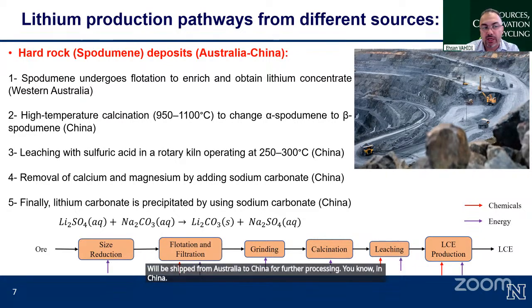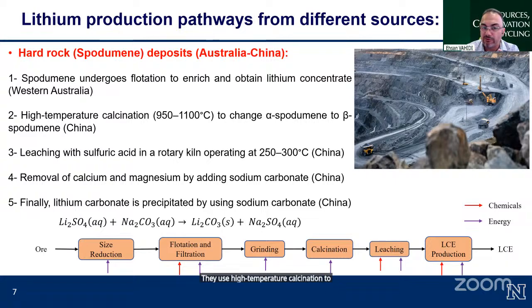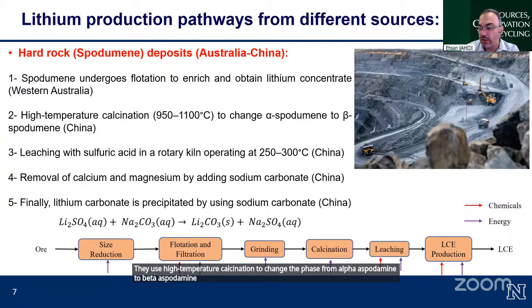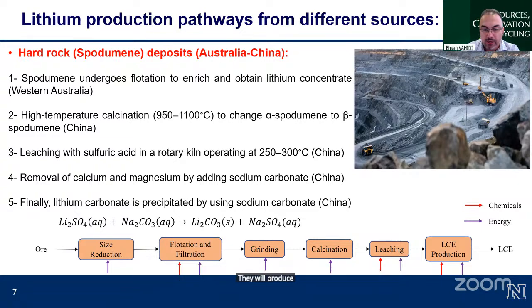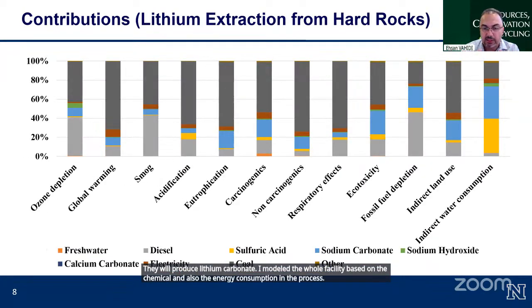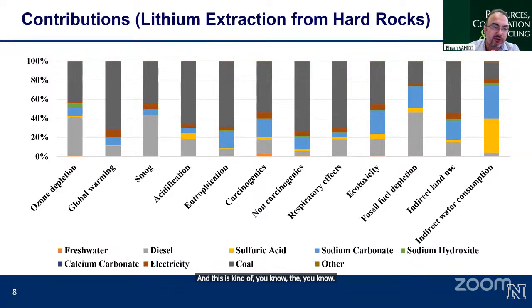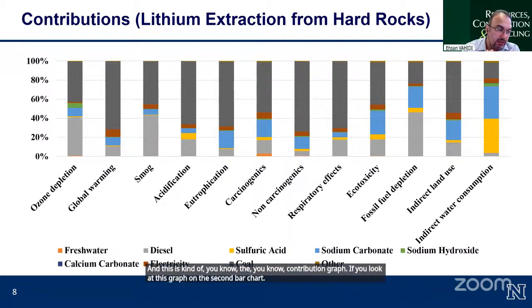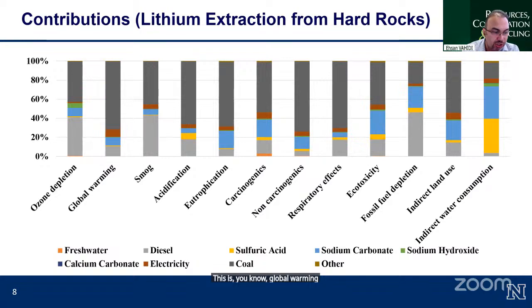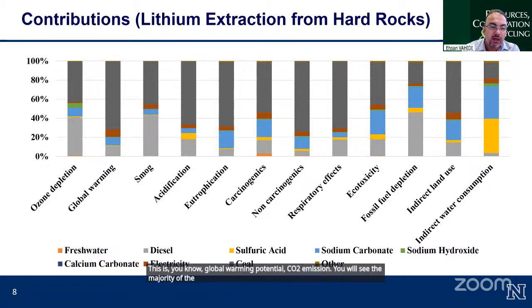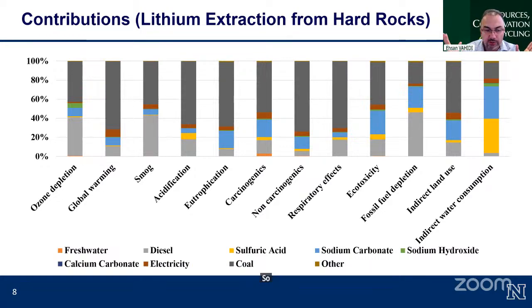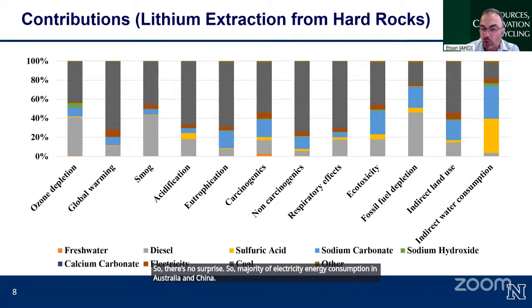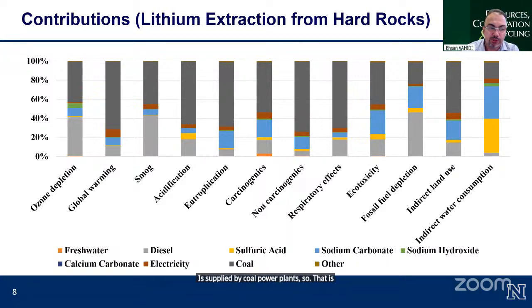In China, they use high temperature calcination to change the phase from alpha spodumene to beta spodumene, and then using leaching at high temperature and sodium carbonate, soda ash, they produce lithium carbonate. I modeled the whole facility based on the chemical and energy consumption in the process, and this is the contribution graph. If you look at the second bar chart, this is global warming potential, CO2 emission. You will see the majority of the CO2 emission comes from coal. There's no surprise, as the majority of electricity consumption in Australia and China is supplied by coal power plants. So that is the major contributor to the process.